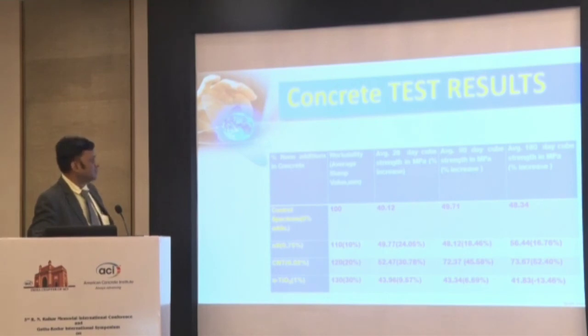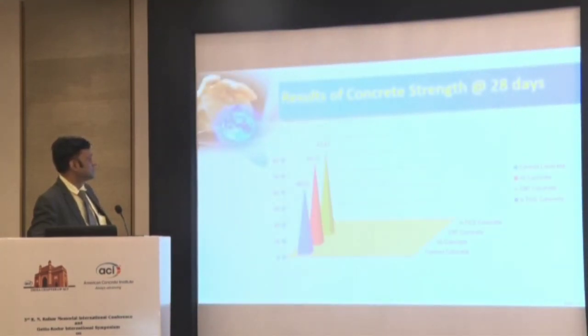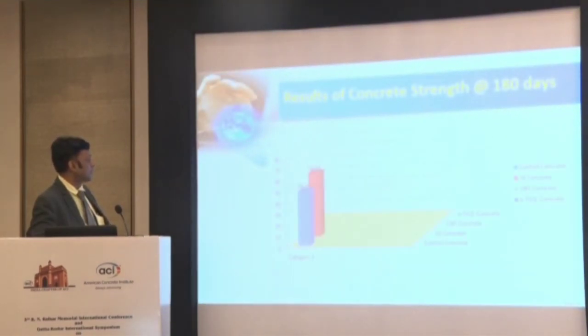Let's see. At 28 days there is an increase and it is decreasing at 180 days. But for CNT it is increasing, 52, and TiO2 is decreasing between 28 days and 180 days. So results, see the increase at 28 days. Now I am coming to 180 days. See the increase. It is increasing more at 180 days.